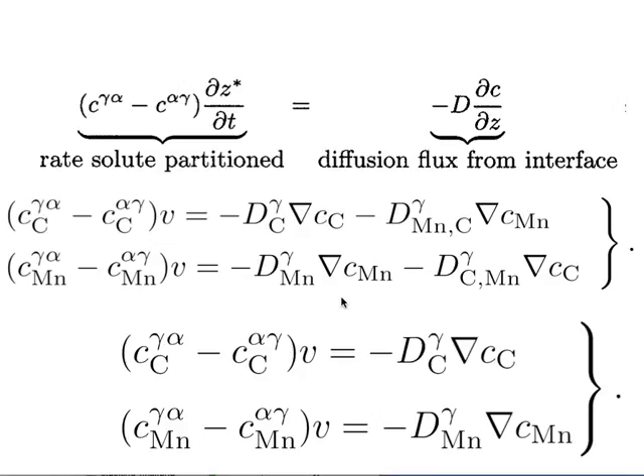10^8, okay? So, no, it's okay. 1,000 is a pretty good guess, okay? And you haven't done a calculation, and I didn't mention the temperature, but typically the difference in ratio is 10^8, because carbon is an interstitial solute and manganese is not.